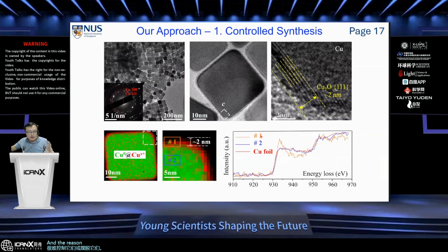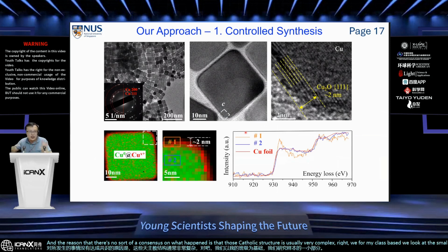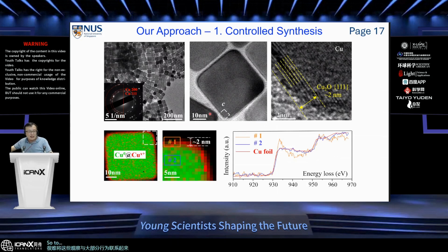And the reason that there's no sort of consensus of what happened is that the catalyst structure is usually very complex, right? For microscopists, we look at a small part of the sample. It's kind of difficult to correlate those observations with the behavior of the bulk catalyst. So to mitigate that, we use the strategy of making a well-controlled catalyst as a starting point. Try to follow what's going on with the catalyst morphology change. So these are some nanocubes, and we found that they're very easy to get oxidized. So you always have a very thin layer of oxide on the top, 2 to 3 nanometers.